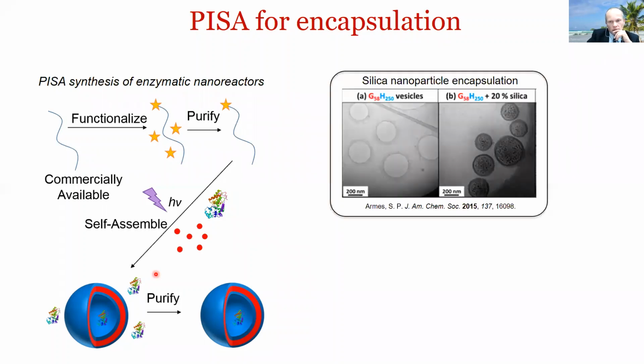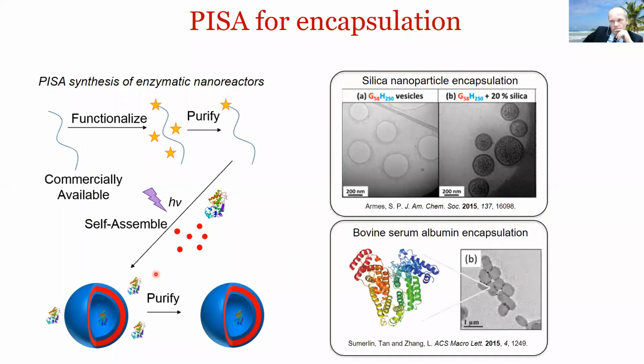And this has been used really effectively by Steve Armes. He showed really elegantly how you could encapsulate silica nanoparticles. And then also from Sumerlin and Tan and Zhang, again, they were able to show very nicely that they could encapsulate BSA. And we've been interested for a number of years in trying to encapsulate active enzymes that might allow us to scope out the function, the protection, but also functionality of such enzymes within our polymeric constructs.